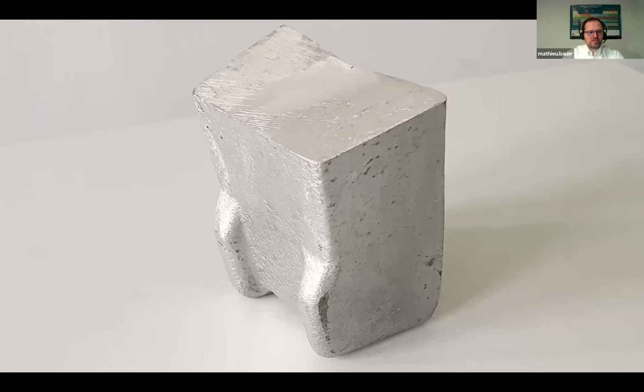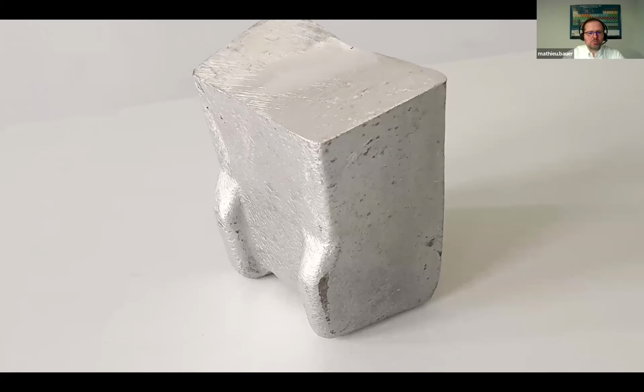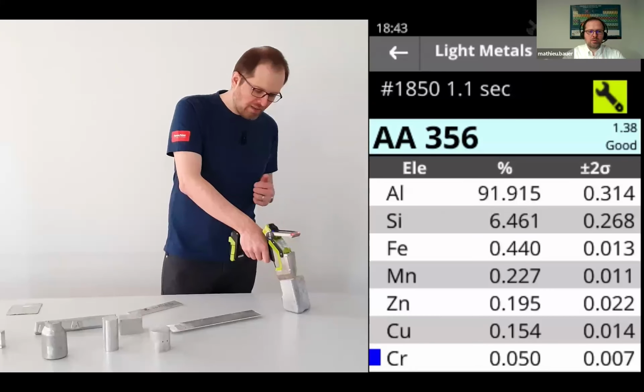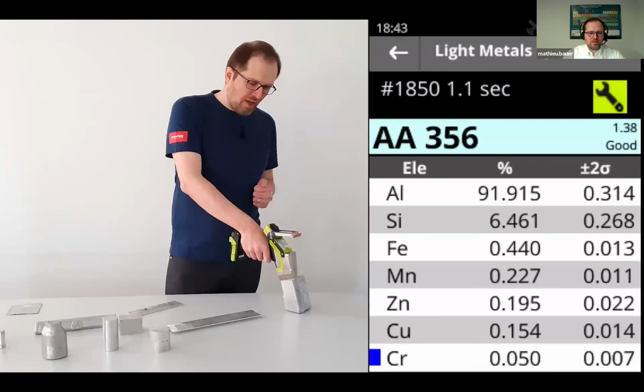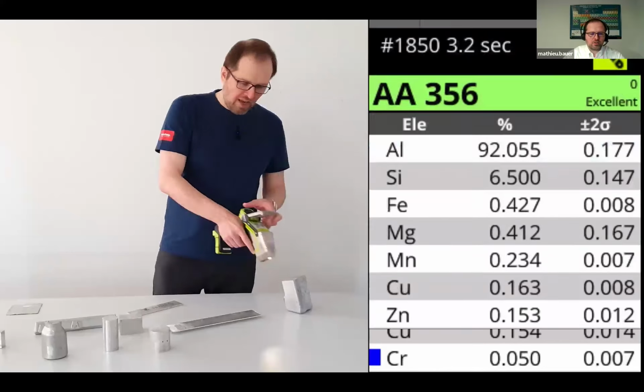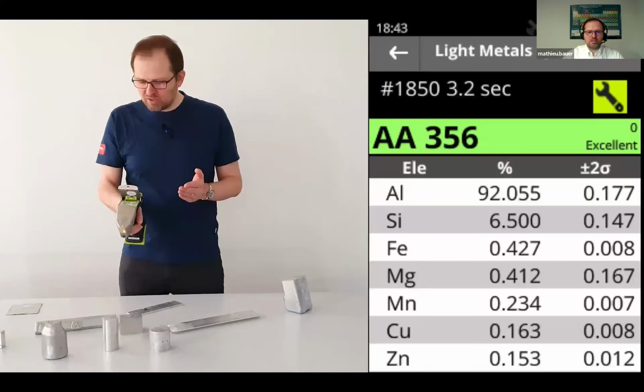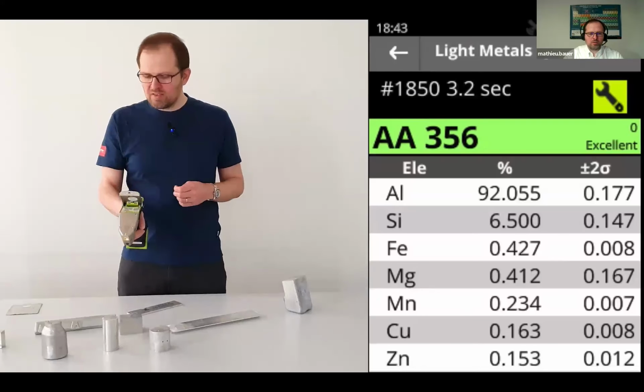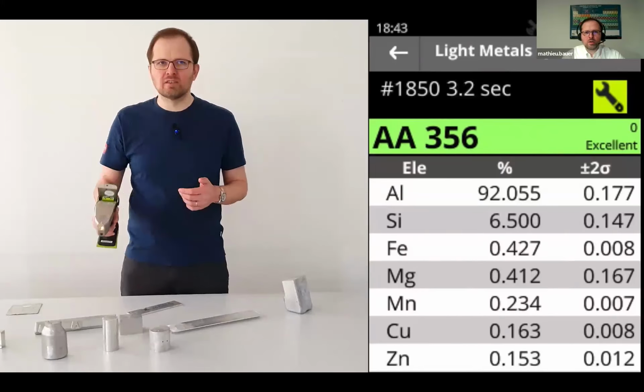Then we have another example here of a cast aluminum alloy that also can be very quickly identified within 1 second, and detect actually the concentration of magnesium within about 3 seconds. So that's just to demonstrate how fast and revolutionary this mode is to sort the aluminum and magnesium alloys in the scrapyard.